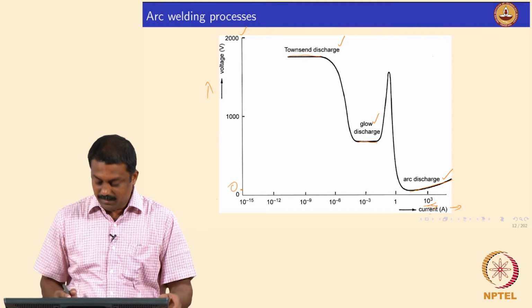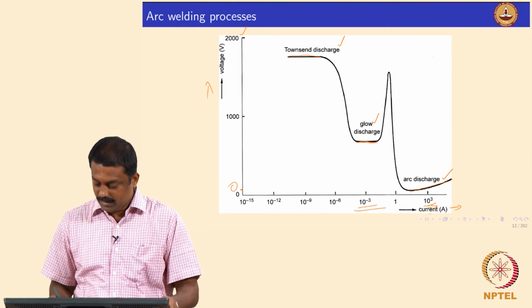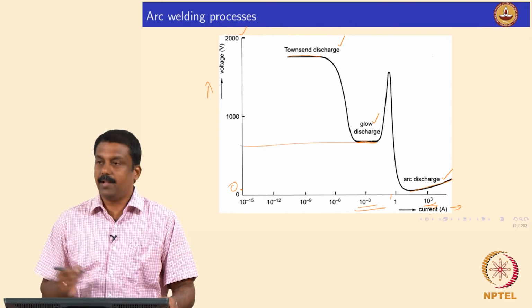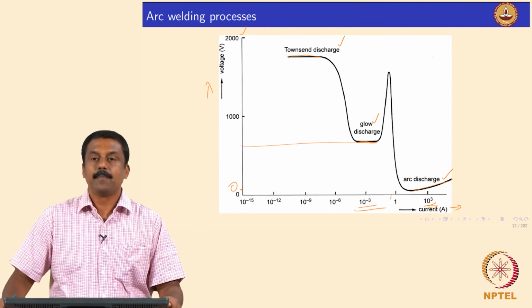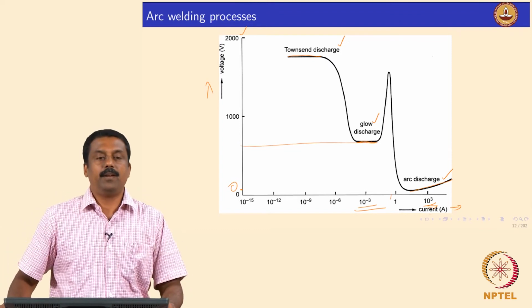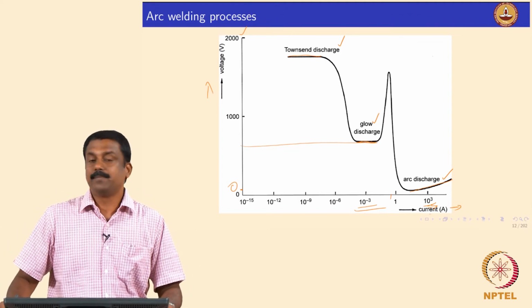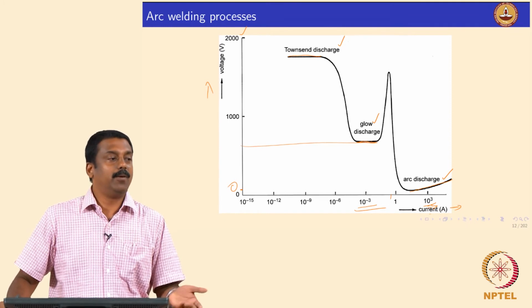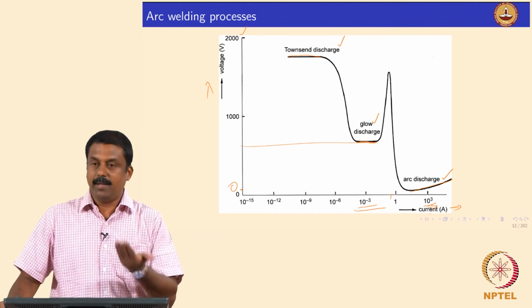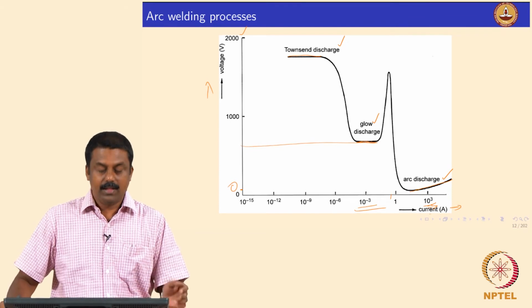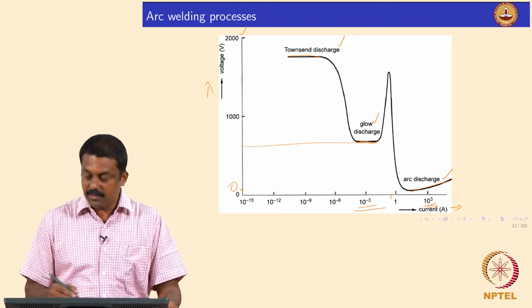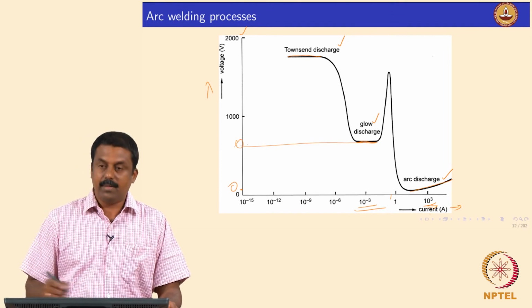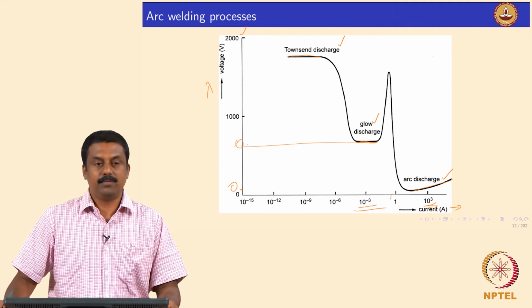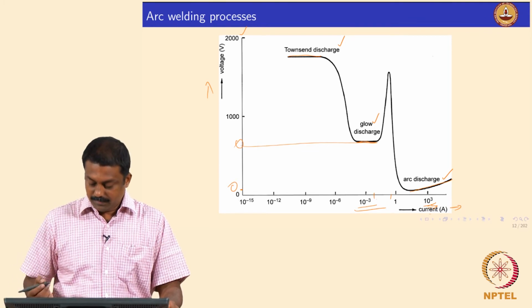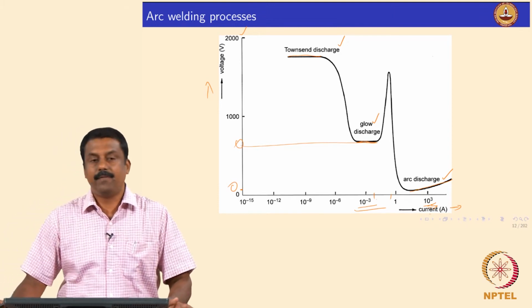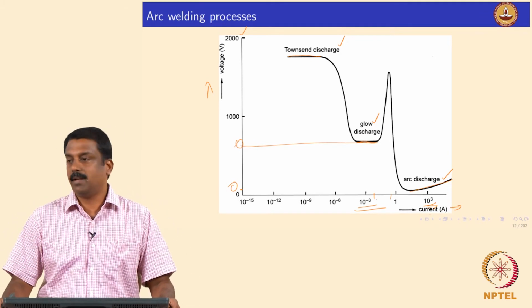So, if you look at these curves, you see that glow discharge happens in the voltages somewhere around the operational voltage. So, what we have about say 200 to 500 volts, where you have glow discharge, or you can also make it lower, but depending on the characteristics of the gas what you use. And generally, commonly you can see that the glow discharge can happen in the voltages somewhere in between say 200 to 500 or so, and the amperage in the range of say 1 to 10 or 15,